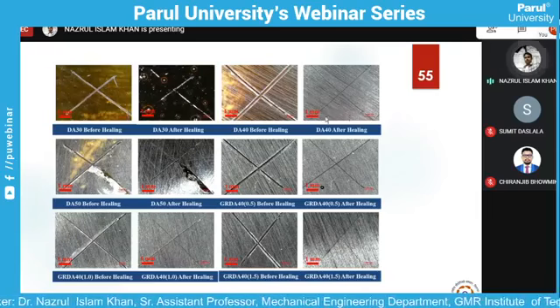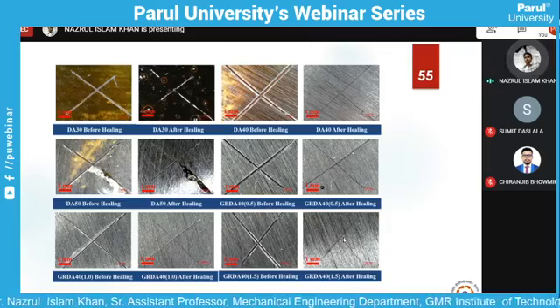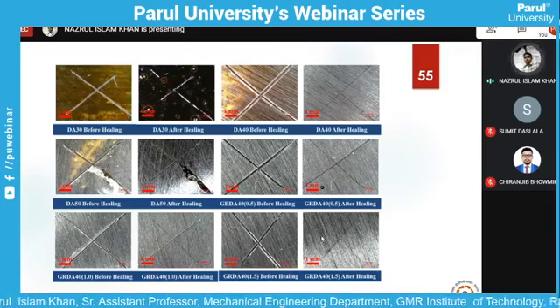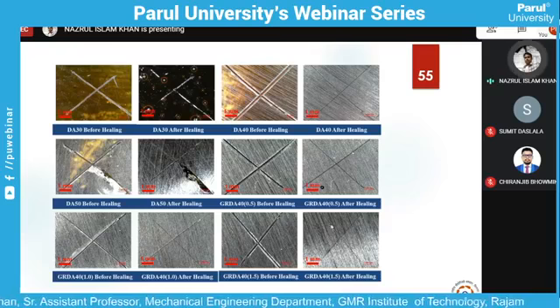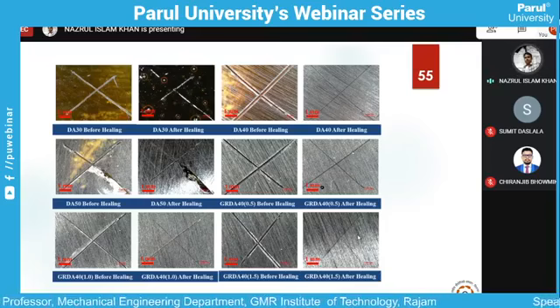We also tested the scratch on the surface and saw that yes, self-healing was possible, because this is the scratch before healing and this is the scratch after healing. The size of the scratch has been tremendously reduced, because with time it is healing the surface.